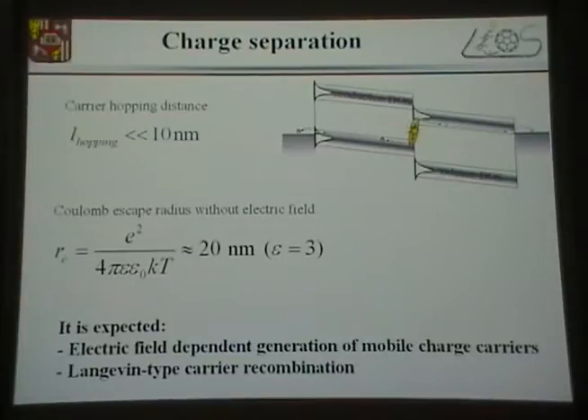And the problem with organic materials is that the hopping distance is much less than 10 nanometers, and at zero electric field, the Coulomb escape radius is 20 nanometers. So you see, charge carriers have, in principle, no possibility to escape each other's Coulomb attraction. Though in practice, in solar cells, we should have some sort of electric field at the interface, which actually helps to split the excitons.